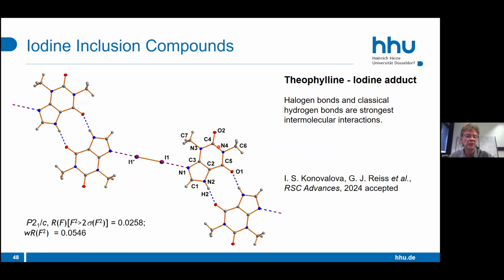Another case that we recently found was again in the theophylline system. Also here we have these hydrogen-bonded neutral dimers, and we were really surprised that these dimers accept an iodine molecule. The interaction energies between the nitrogen and the iodine are in the range of strong hydrogen bonds. So halogen bonds and hydrogen bonds have the same quality in this system, and it was Irina Konovalova.